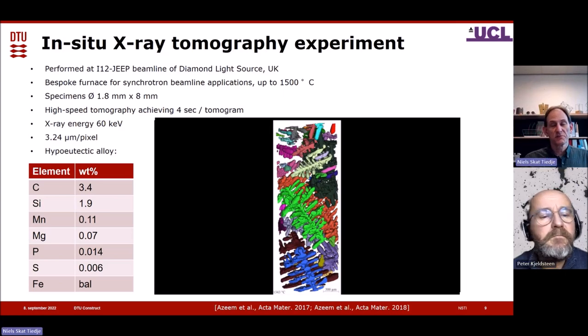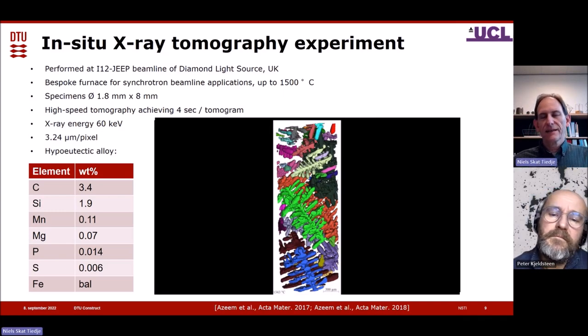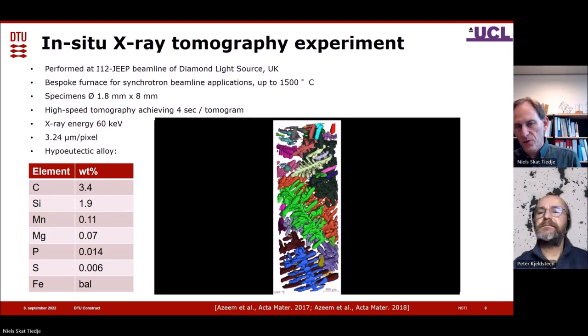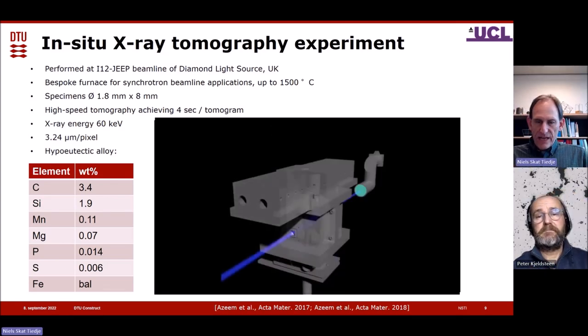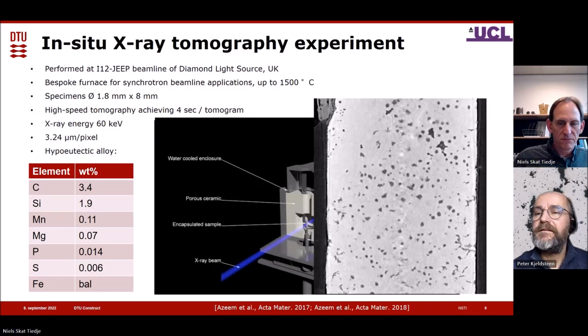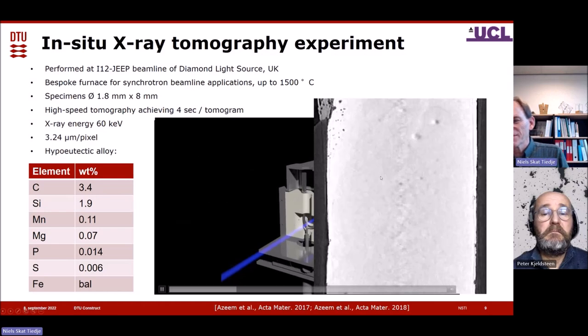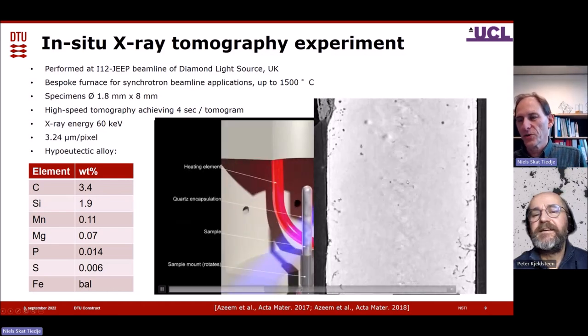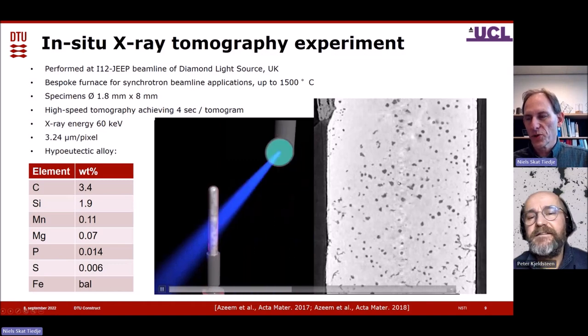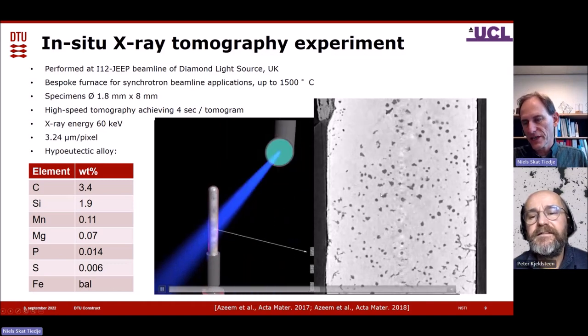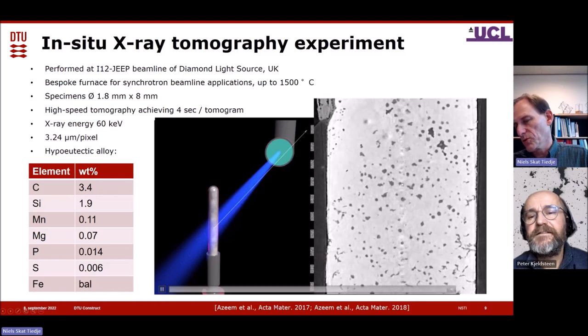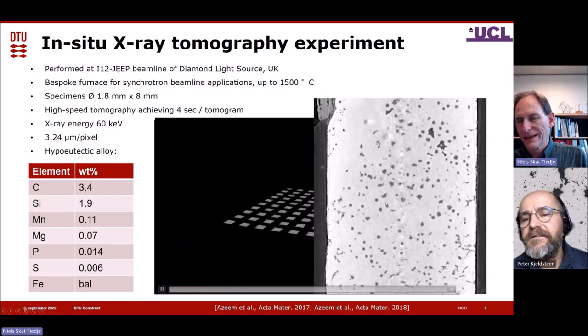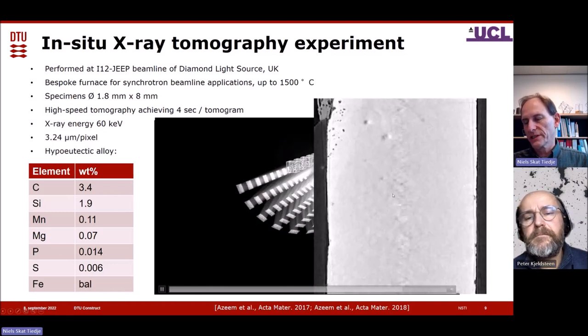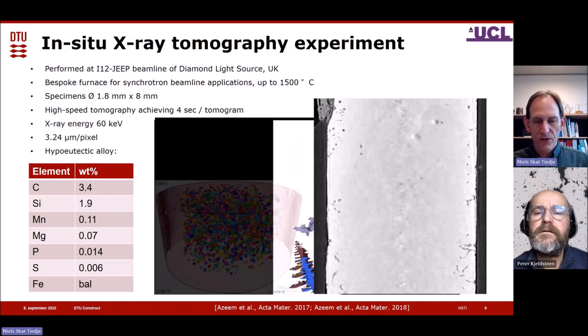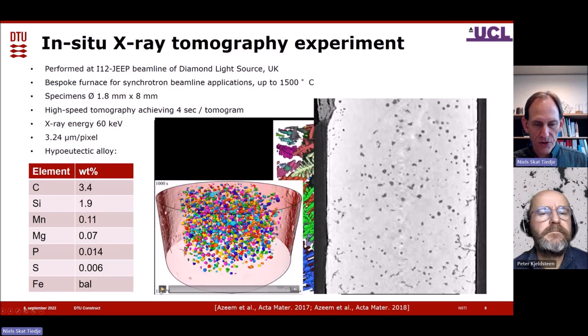And this sounds very, very simple. And in theory, it's very, very simple. But to get from the experiment to the first image takes 3 months. And then you have something that is shown, more or less shown on the right here, a stack of 2D images with time. Here we have a section through the sample, and you can see in this case most of the black dots are graphite that form. And then you have to stitch it together to 3D geometries, and you have to segment and pick out the graphite. So in the end, you end up with a video that is shown here.